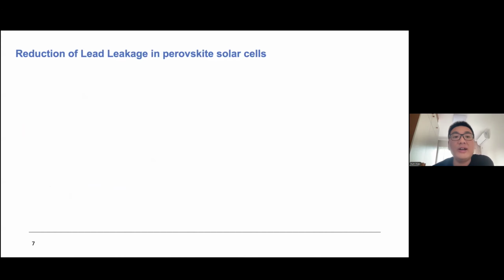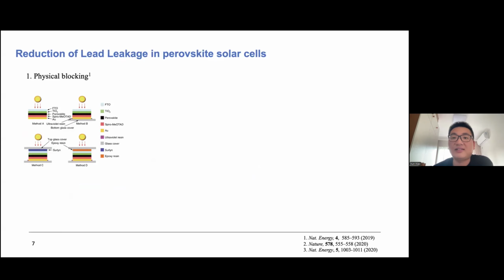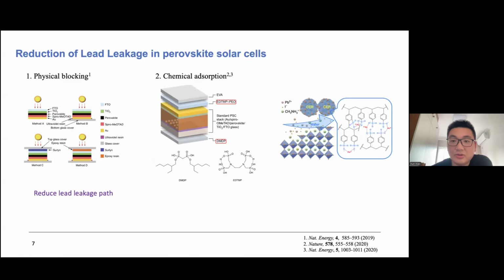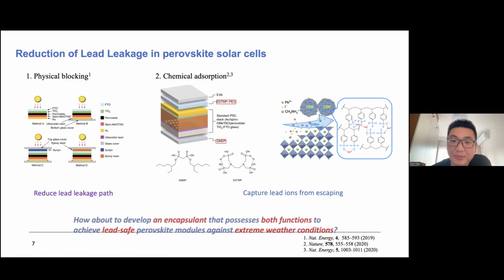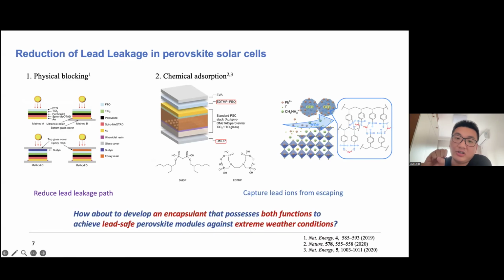Previously, when I tried to address this lead problem in perovskite solar cells, the first work I did was on how to reduce the lead leakage. Usually there is physical blocking, as I explained before, like an encapsulant physically blocking the lead leakage, or it can introduce chemical absorption, using lead absorbing materials, so that if the lead ions try to escape from the perovskite solar module, they will be captured and the lead leakage blocked. At that time, we were thinking about whether we could develop an encapsulant that has both of these functions.